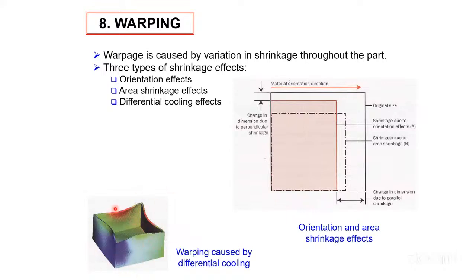See here, a rectangle or maybe a square type of article is there, but see how it gets deformed. It is not a straight wall thickness. This happens due to the shrinkage throughout the part. There is a lot of shrinkage taking place here and here, and that's why the article is deformed completely. It shows warpage at all corners and at the center. Therefore, why does this happen? Due to the variation in the shrinkage. Shrinkage takes place, but there's a lot of variation.